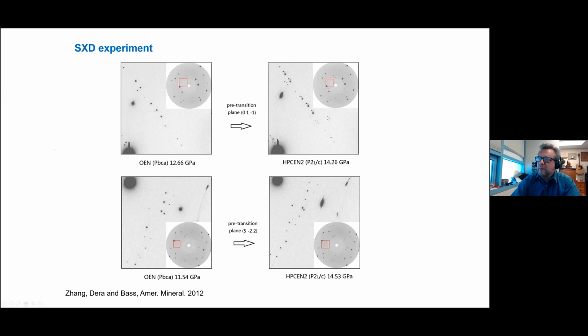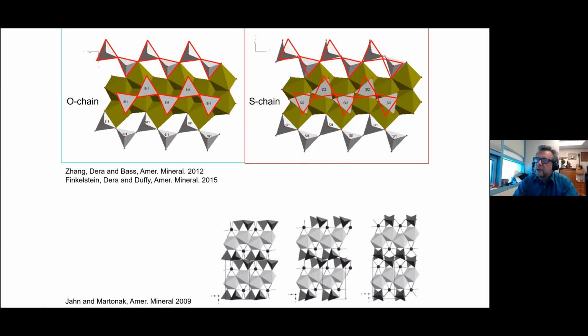But the experiment yielded quite interesting information. This is a diffraction pattern. You can see that because the sample is a single crystal, not powder, the diffraction signal is present in the form of these peaks, spots, rather than Debye-Scherrer rings. So the geometric pattern of these spots tells us about symmetry and the unit cell of the crystal. You can see as we increase pressure between more or less 10 and 14 gigapascals, the pattern becomes significantly different. We have additional peaks that form, indicating that the unit cell and symmetry underwent changes.